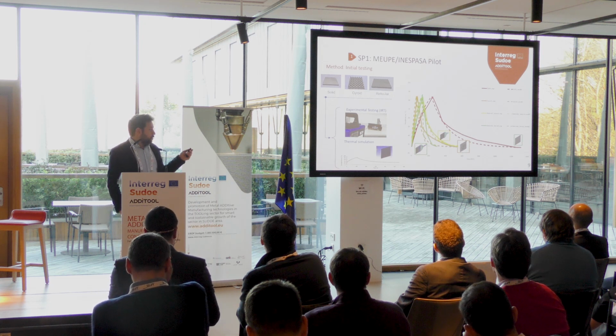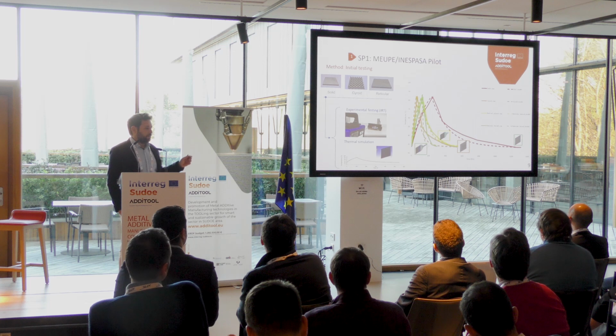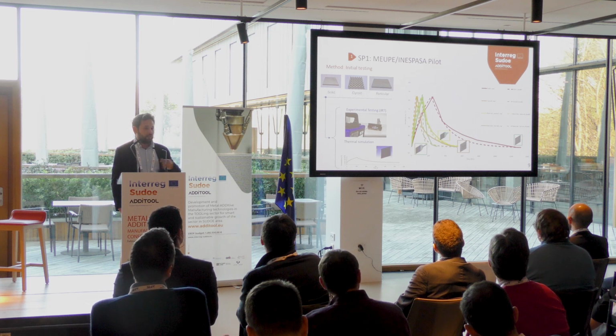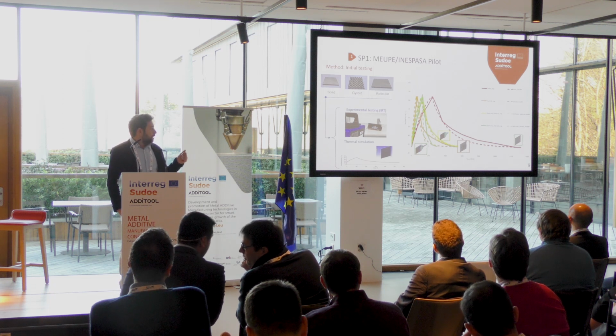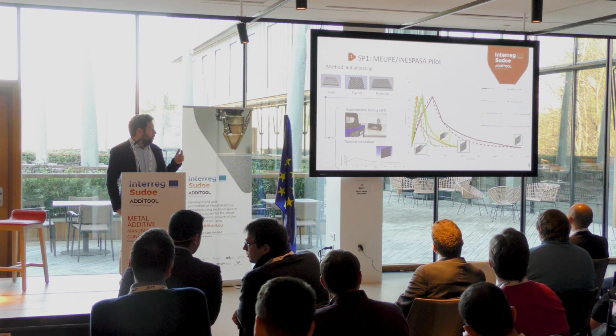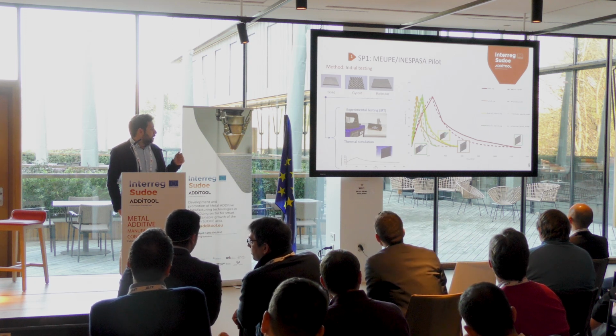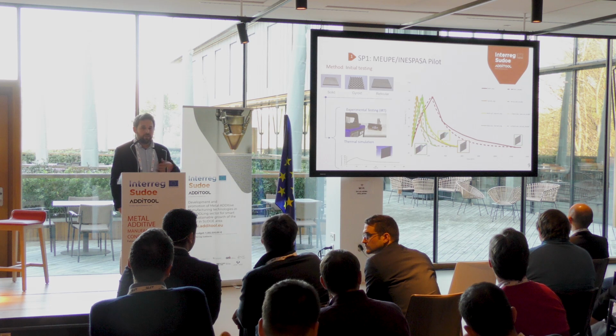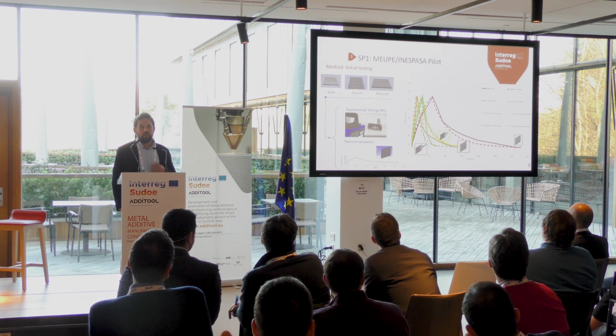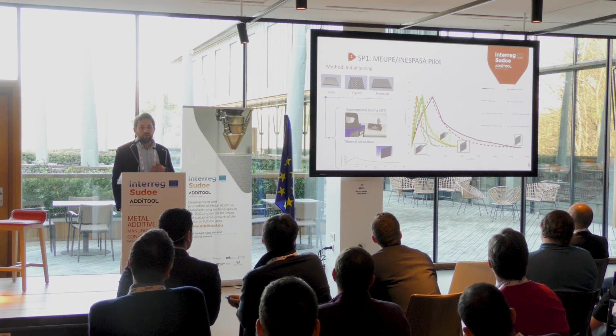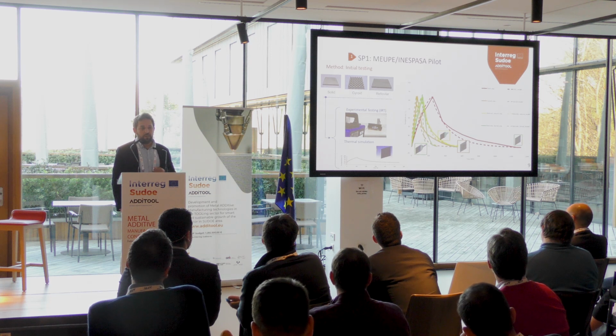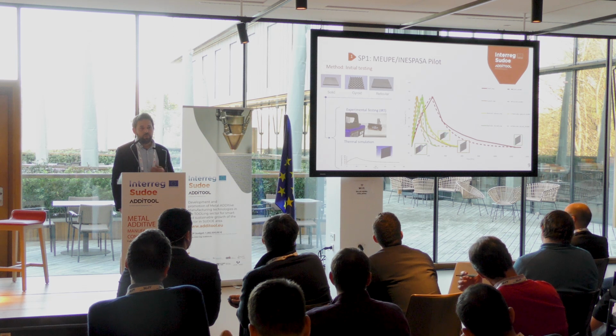So as the main conclusion here, the reticular internal cavities sample is a better approach than gyroid. The other conclusion is that if we reach high temperature very fast with the reticular, we have to make something else to avoid the motors reaching that temperature, not to avoid the stop.